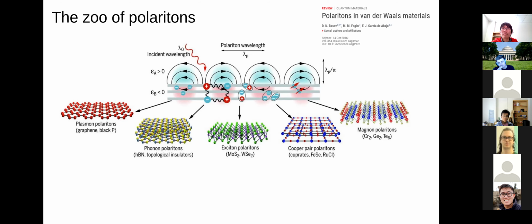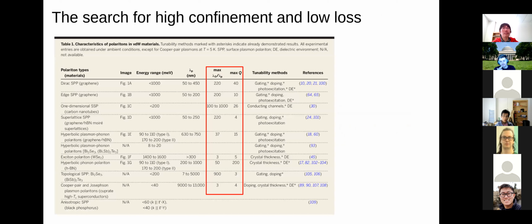Now, why do we care about these kinds of things? One reason, as I mentioned earlier, is that these excitations can achieve very strong confinements of the wavelength, again, meaning that the wavelength is much smaller than the wavelength of something at a similar frequency in a vacuum, for instance. So this column on the left that's highlighted for a bunch of different flavors of surface polaritons is the confinement factor, which tells you about that level of sub-wavelengthness. And then the thing you're fighting against here in any of these systems is loss, as characterized by the propagation quality factor. In other words, how many wavelengths the thing is going to propagate before it gets absorbed through some kind of electron or phonon scattering process.